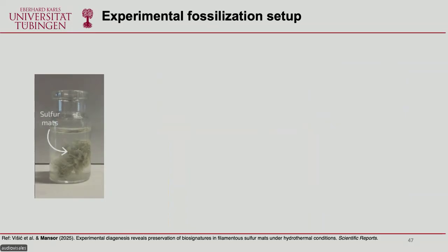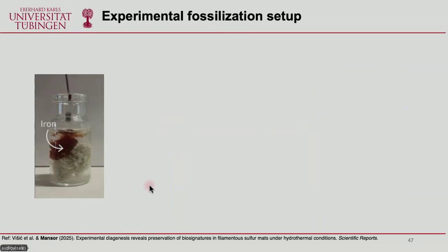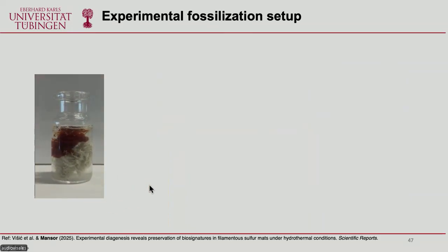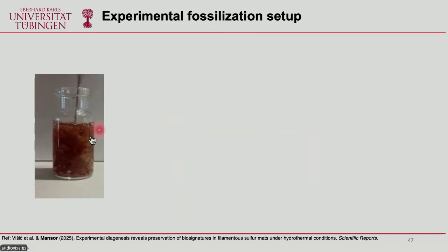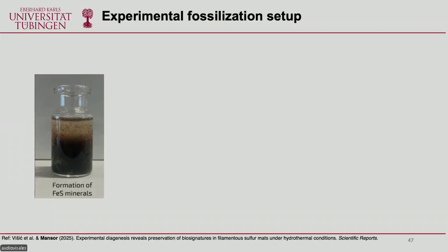This is a typical experimental fossilization setup. Here, starting from the sulfur mats, we add a source of iron because we know that when they get buried, they will get exposed to iron. We mix them together to observe how they attach to the mats. And then we add sulfide, which causes the reaction to go really rapidly. Iron minerals transform to iron sulfide minerals, and within minutes, you see everything turn black.